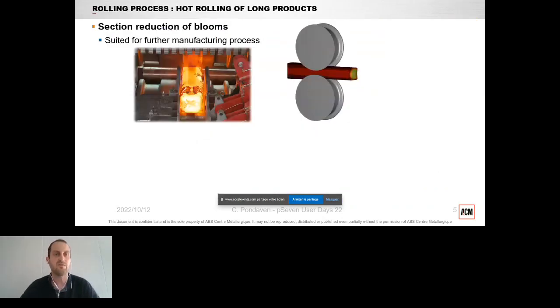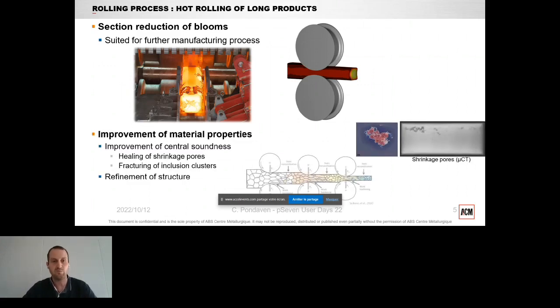So today we will be focusing on the hot rolling process, which is a forming process aiming at the reduction of the initial section of the bloom to produce bars suited for further manufacturing processes, for example, for forging of crankshafts or other automotive parts. And during this process, we also experience an improvement of the material properties with the reduction of the shrinkage pores generated during casting, and also with the fracturation of the clusters of inclusions during the rolling, and we also experience the refinement of the structure of the material.